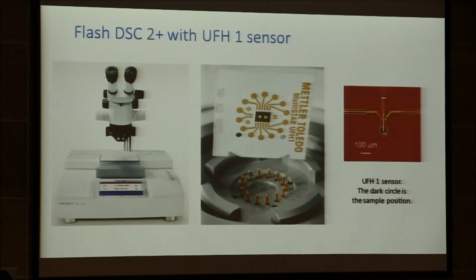And this one works on the basis of solid-state chips. They are hit with a flash of heating, and they are relaxed at heating and cooling rates which are thousands and tens of thousands of degrees per second. Now you can guess that if you're going to do something at that speed and get something reasonable for a finite sample, it has to be very, very small. And so this is the frontier. This will allow us to do 10 micron samples.